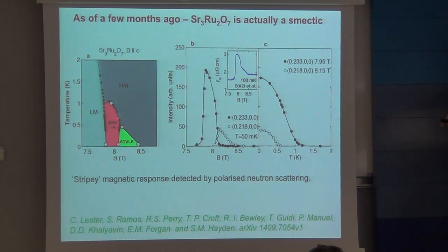If you've got good eyes, you'll see that he's insisting that this is a standard spin density wave in the way he interprets. My point is, it's incredibly interesting what he's done, but you can't ignore all the thermodynamics. The thermodynamics still look extremely strange. So this is not a standard spin density wave. This is a state with some form of spin texturing. In our language, it's smectic, but we do not yet fully understand what the significance of this translational symmetry breaking is.